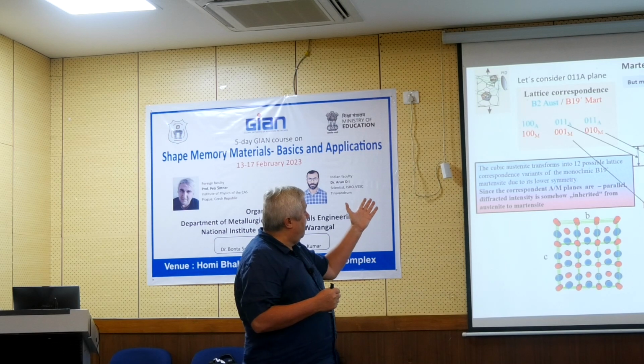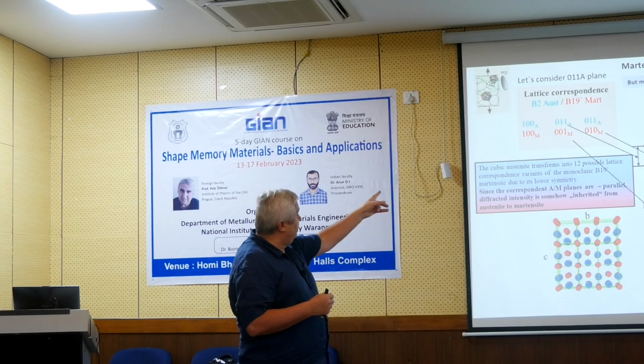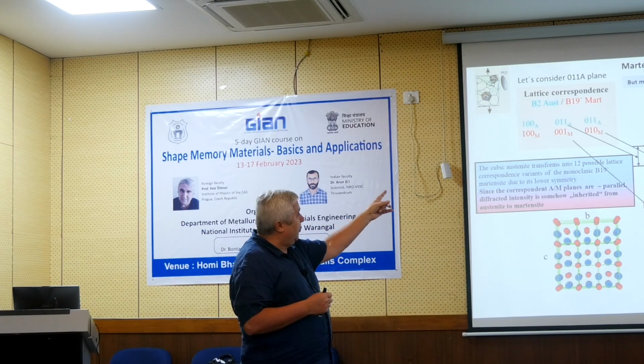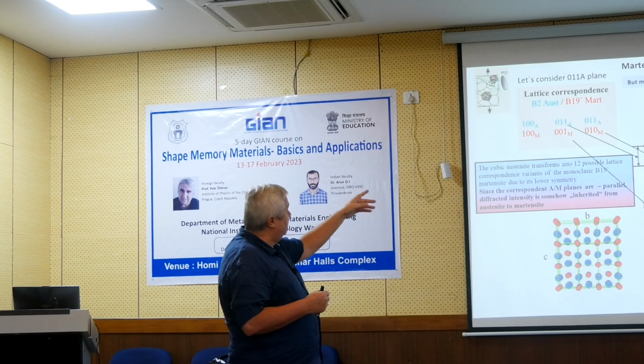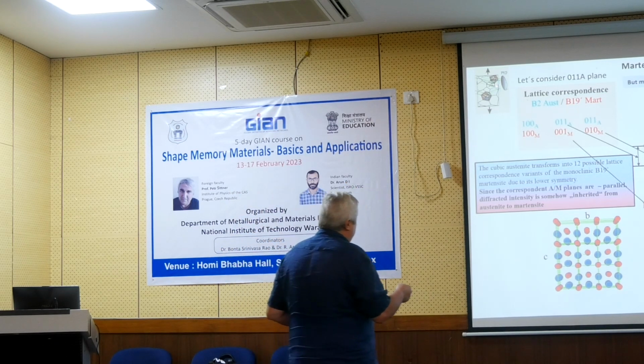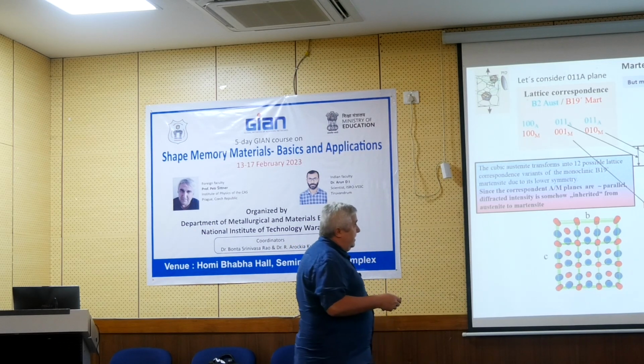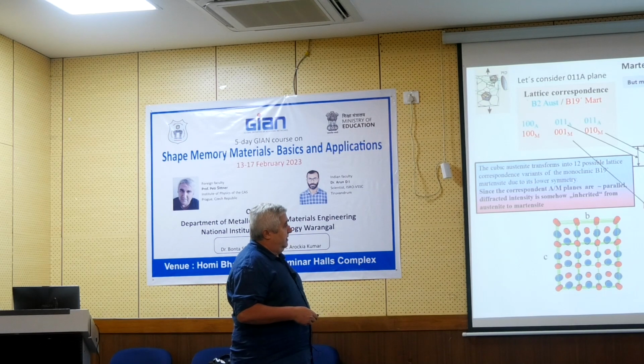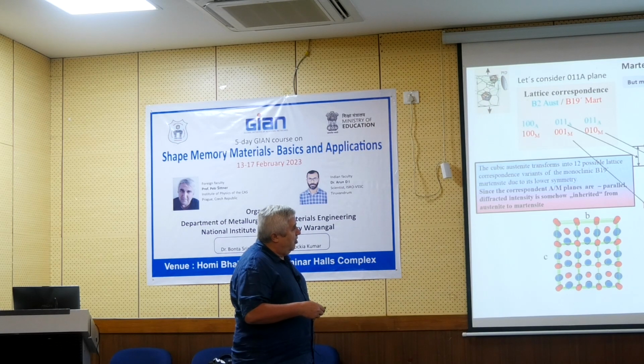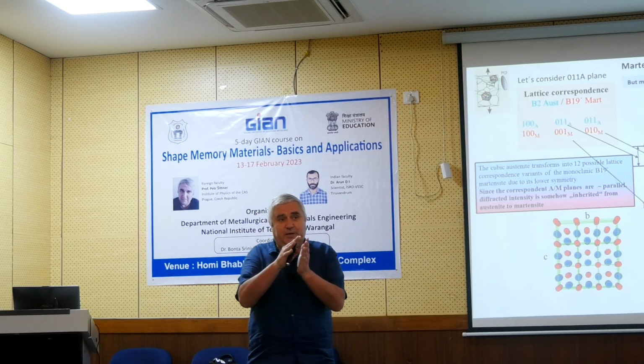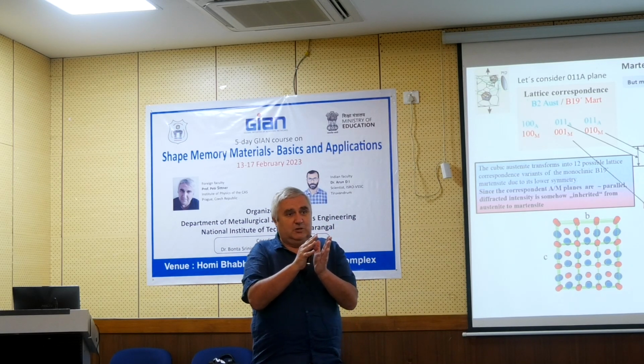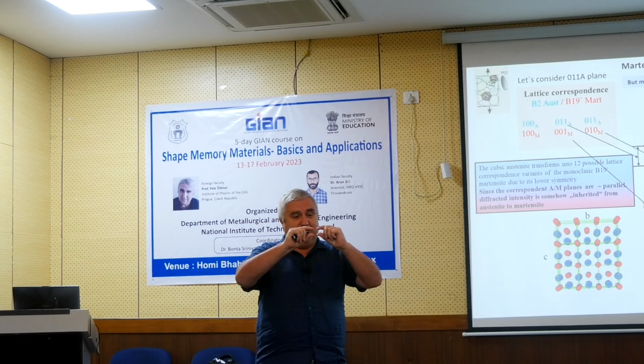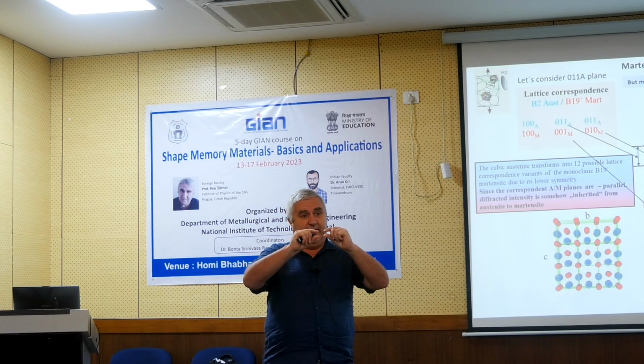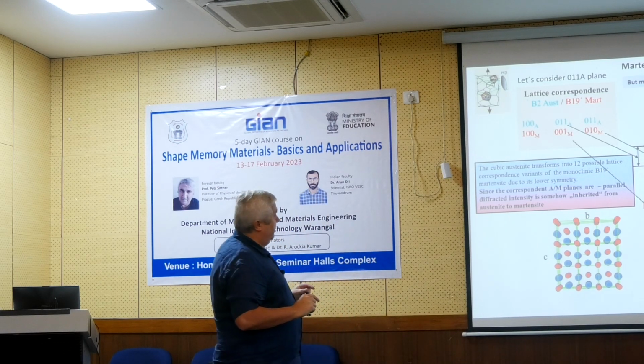So this is the basic law, and whatever the variant is, if you properly index the austenite and martensite, you will always find this relation. But one should be very careful. Here this is the austenite and this is the martensite, and I am saying lattice correspondence. The correspondence means that these planes are almost parallel, but they are not exactly parallel. There could be a little rotation, but almost parallel. And the lattice spacing, which was like 3, changes to 3.1 or 2.8 or something like that.